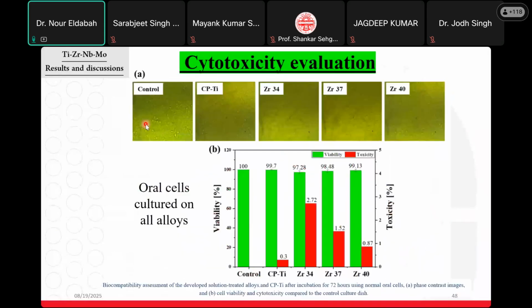The final and most important test is the cytotoxicity, which will tell you if your alloy is toxic or non-toxic to the human body. It is cell culture. You culture cells on the surface of your alloy and incubate it for a certain duration of time. In our case, we first used normal oral cells, which exist in the mouth in case of dental implantation, and we found that no toxic effect was caused by our alloy, nearly a low toxic effect of around 2.7 percent when compared to the control cell, which indicates a good viability of our alloys.